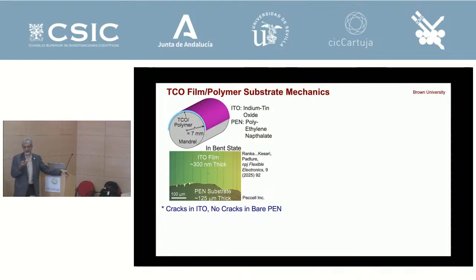Hundreds of papers are published on this kind of work, and you normally think that yes, ceramic cracks, polymer doesn't crack, because polymer is, compared to ceramic, infinitely tough, right? But my student decided to do, so this is the toughness. The toughness of PEN is about 55,000 joules per meter squared. This ceramic is about 5, perovskite is about 2, right? So they're all very brittle materials, right? So there's no perovskite here, it's just the TCO or ITO, right?